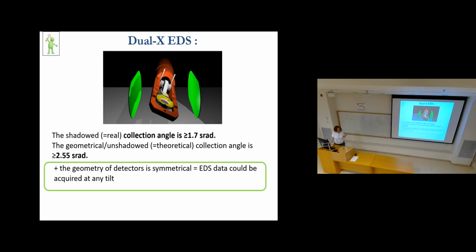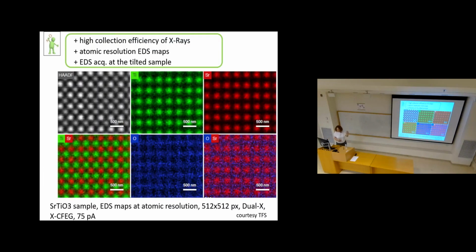And for example, if we have an interface and we orient it so that we see it parallel, the interface plane is parallel to the electron beam, we'll acquire EDS at this position without thinking about how to increase the amount of photons or something like that. And as a result, still these maps were not acquired at our TEM. We still didn't have enough time, but these nice atomic resolution EDS maps were acquired at the same instrument. And this is a strontium titanate sample oriented properly to see the lattice image.